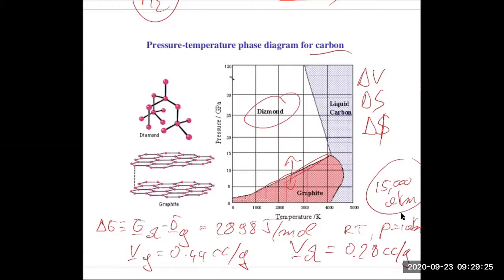But in reality, of course, at room temperature the kinetics are so bad because you're going from graphite, which is totally different bonding, to diamond, that people want to do this at high temperature. But you see the problem here, right? At high temperature, the transition pressure actually becomes much higher as well. So that doesn't work particularly well. So people do it by seeding now. And it's actually really not that hard anymore to make diamond by seeded growth. So you take a small diamond nucleus and you grow it out of a carbon containing atmosphere under high pressure, and you can make diamond.